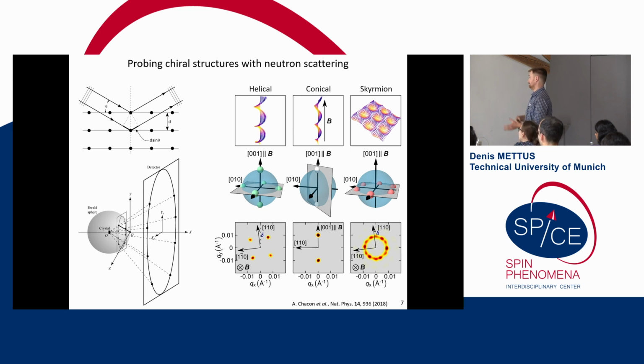And in practical terms, it means that we have some real space structures. We transform them to the momentum space. For helical structures, it's just very nicely ordered spots. And since there is a triangular lattice, you have a six-spot scattering pattern. And this is the Ewald sphere, like here. What we measure is the cut of the Ewald sphere with a plane, which gives you the detector image.